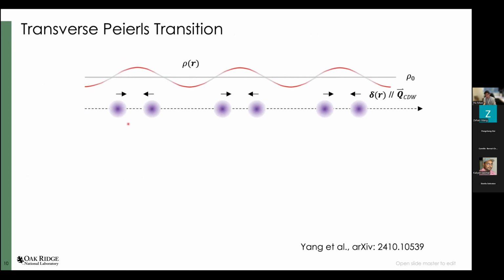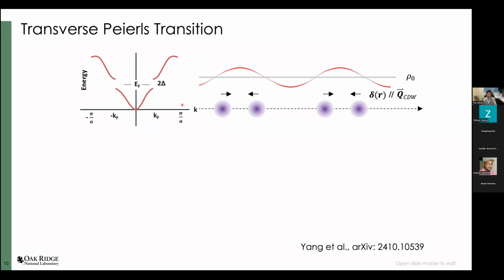Before that, let's review the fundamentals of a charge density wave in 1D. Here I sketch the famous Peierls transition. Quite interestingly, in the Peierls model, he only considered the coupling between the electron and the longitudinal acoustic phonons. The reason is that for a single atom in one unit cell, the main energy cost is from the volume change. If you go back and check, you will find that for the electron-phonon coupling, the longitudinal acoustic phonon always dominates. And once you have a Fermi surface at a high filling, you favor a Peierls transition, and you open a gap at the Fermi level. That's the story that everybody knows.